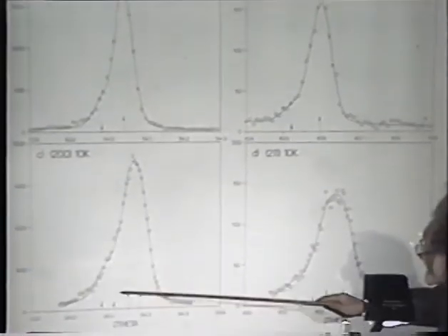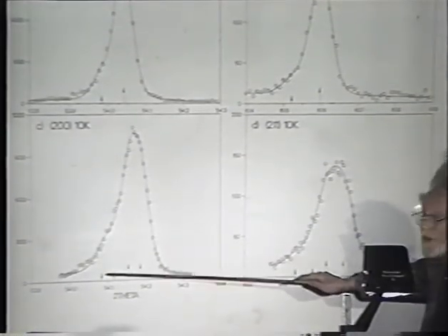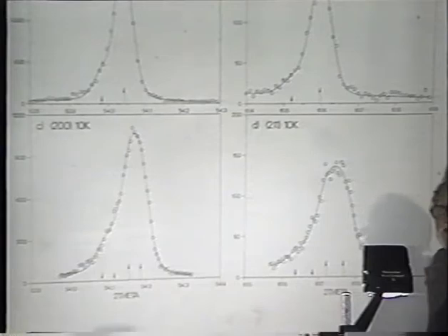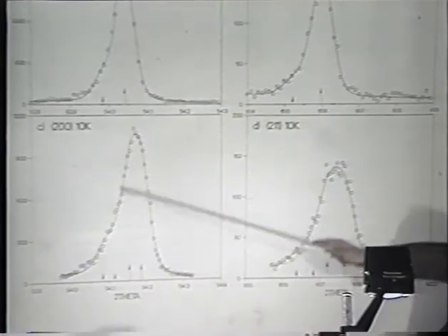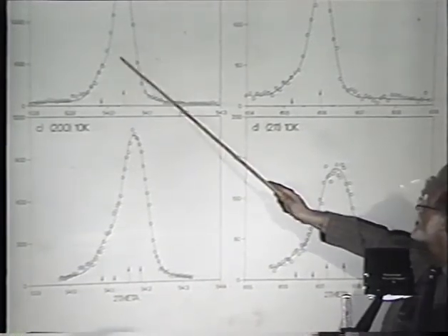And the same thing for 211. When we cool down, the peaks broaden and we fit them with 2 peaks split now. And we split the minor one as well, although we don't know that it's actually split. But certainly we see a broadening on cooling and a major and minor phase.